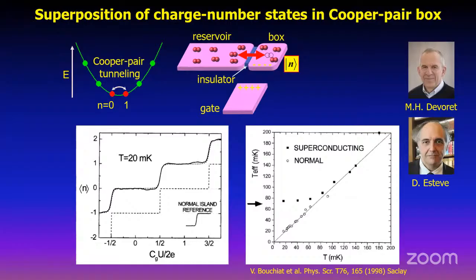So here, for example, in Michel Devoret's group and Daniel Esteve's group in Saclay in France, they looked at this device and at the behavior of the ground state, to see the expected charge number state in this device as a function of the gate voltage, showing this discretized step. As you sweep the gate voltage, Cooper pairs are introduced one by one into the island. But if you look carefully at this step, if there's no coherent superposition, this step is expected to be infinitely sharp, vertical. But because of this superposition effect between these two states at the step, there's always some finite slope for rounding because of the superposition.